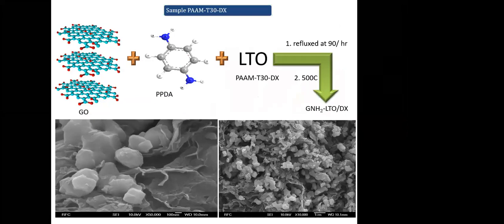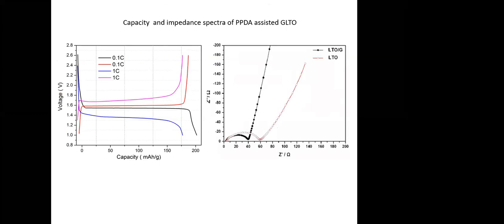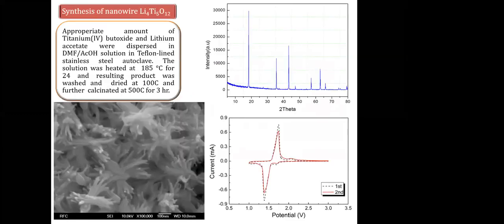Okay, similarly, here we have taken the sphere, means like uneven shapes. So we tried to modify the shapes of graphene and LTO. Different reaction parameters are changed, and by the hydrothermal method, using DMF and acetic acid as a solvent, we get flower shaped graphene LTO. So you can see this flower shaped LTO is seated on the graphene, and it is matching with the full phase of